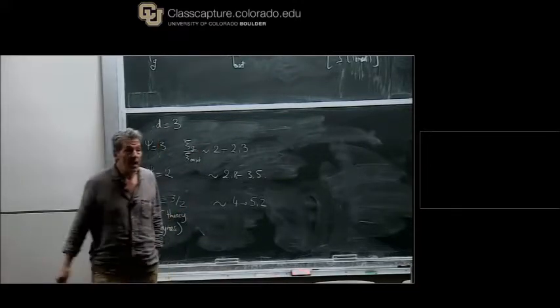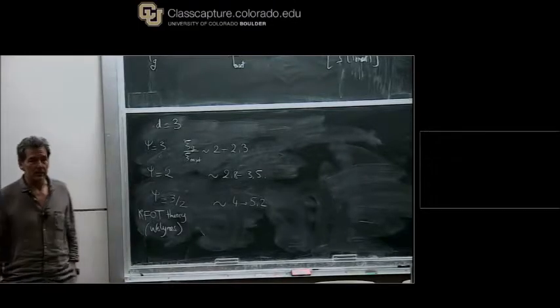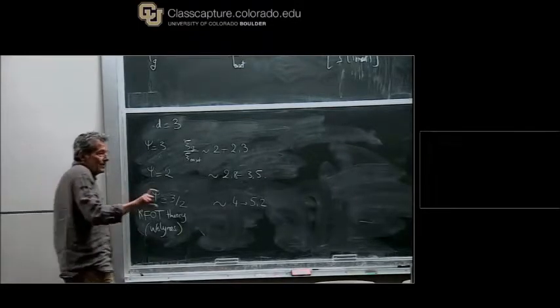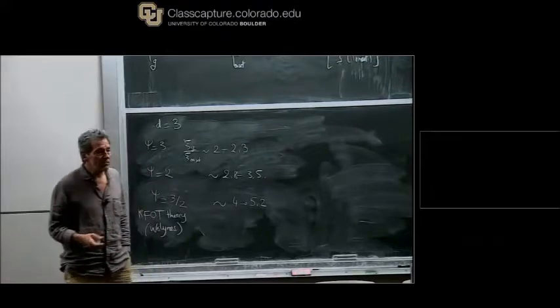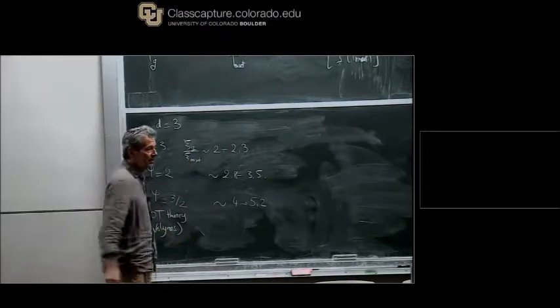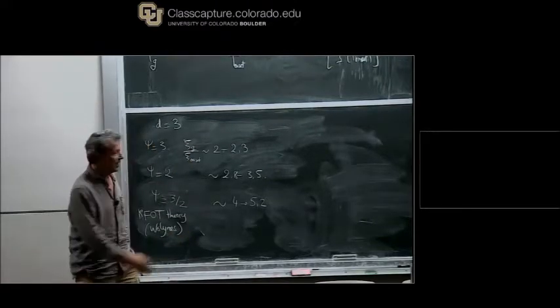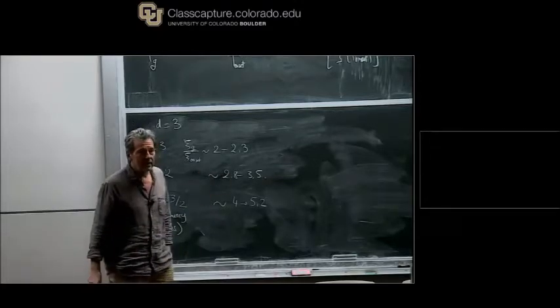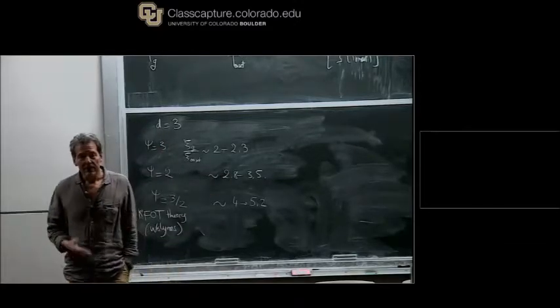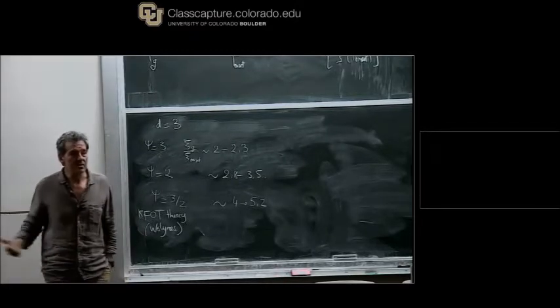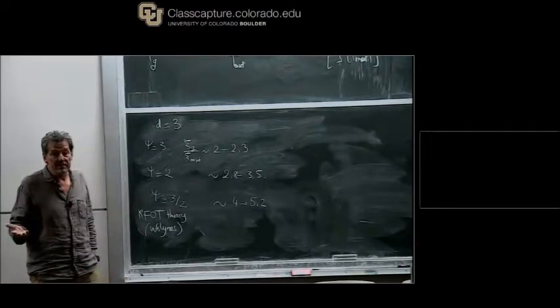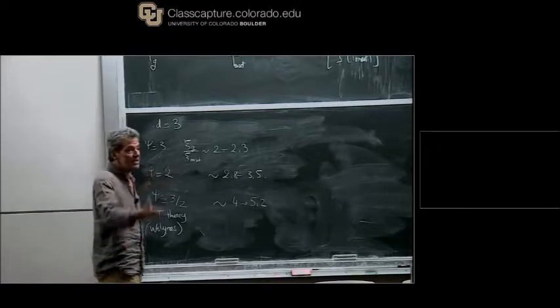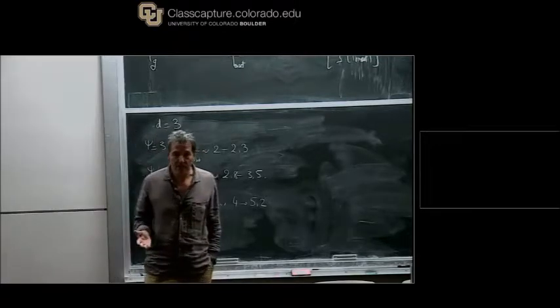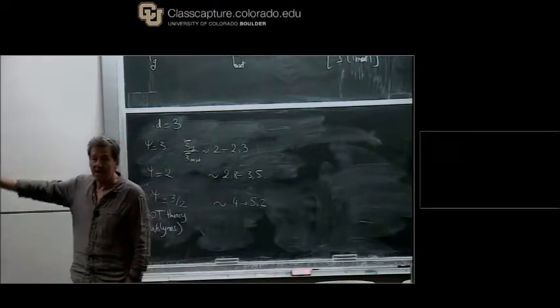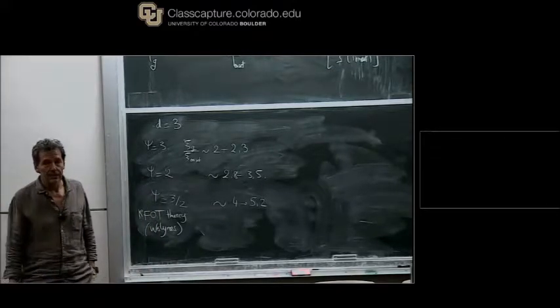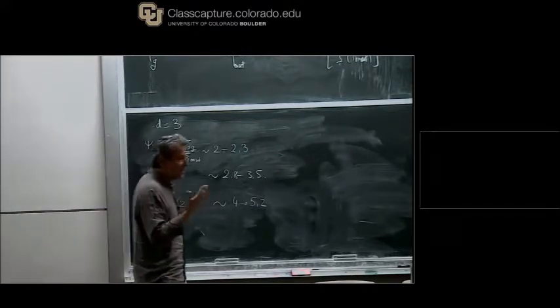And for instance, this is what happens in the case of the random field Ising model. On the other hand, you can also say, well, if the correlation length increases just by such a small amount, are we sure that the connection we are making between the relaxation time and the correlation length is indeed valid, and that we're not just missing another type of explanation that would be valid for explaining the slowing down? Okay, so this is something that one has to keep in mind.